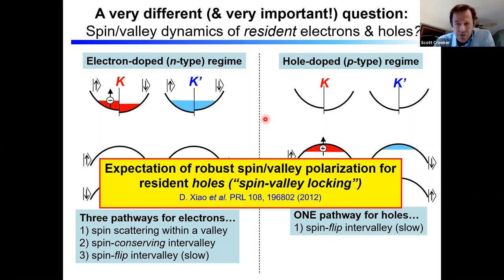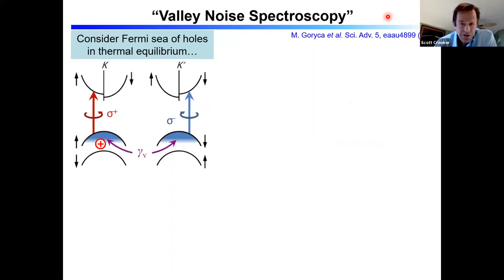Now, using conventional ultrafast pump probe types of experiments, it's possible to measure these effects. In a conventional pump probe experiment, you'd come in with light, you'd blast in polarized electrons and holes, and then you'd shake up the system and it would relax and you'd measure that lifetime. Our group has done a lot of these, but there's always the criticism that in these pump probe experiments, you're always injecting minority carriers and those could get trapped in dark states, and maybe the signals you're measuring are masquerading as something else. So the question was, can we measure valley dynamics without pumping the system? So it's ideal for noise spectroscopy. In these materials, we have very clean optical selection rules, circularly polarized selection rules.